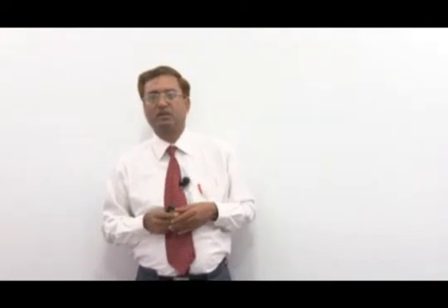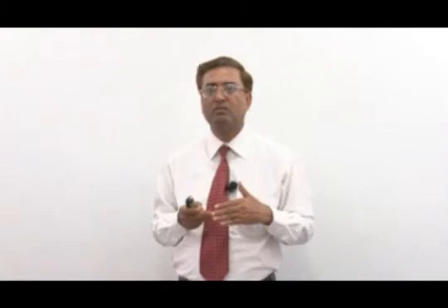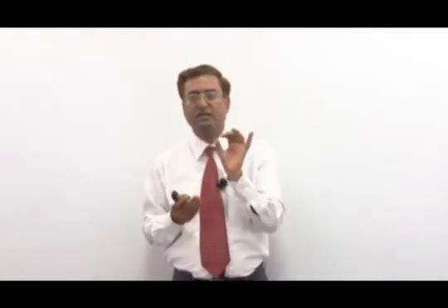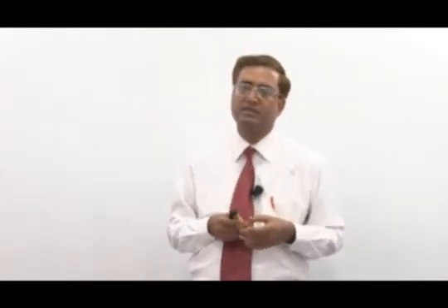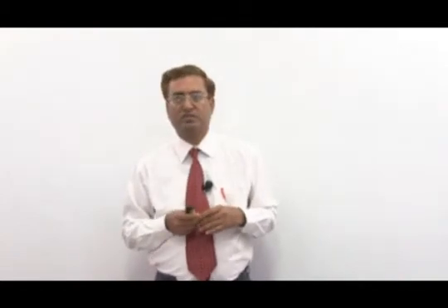So one can then write down this particular equation, that is sigma x plus d sigma x multiplied by h multiplied by z, plus 2 tau xy multiplied by dx, because 2 faces, dx is the element thickness that we are going to take, multiplied by z, then minus sigma x multiplied by h multiplied by z, and this summation has to be 0.